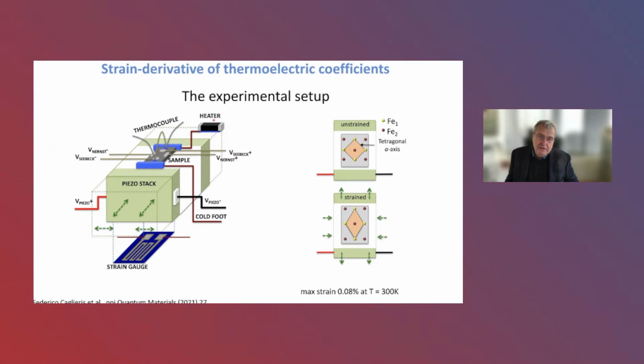So we have a heater here. So we apply a temperature gradient here. Using a thermocouple, then we can measure the temperature gradient, which we obtain by the heater. That's one ingredient. And using these contacts, we can measure the thermal power or Seebeck effect. And if you apply an additional magnetic field perpendicular to this stack and measure the transversal voltage, we can also measure the Nernst effect. And this we did also for these samples.